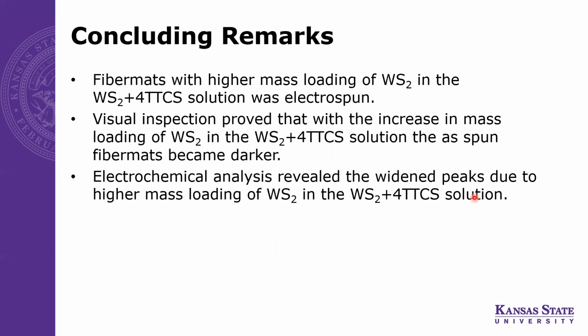To conclude, fiber mats with higher mass loading of WS2 in the WS2+4TTCS solution were electrospun. The visual inspection proved that the increase in the mass loading of WS2 in the WS2+4TTCS solution actually made the as-spun fiber mat more dark. Electrochemical analysis revealed the widened peaks due to the higher mass loading of WS2 in the WS2+4TTCS solution.